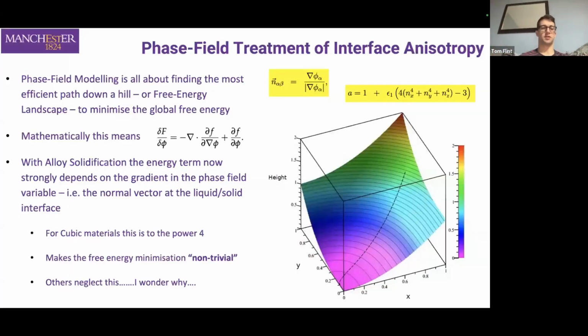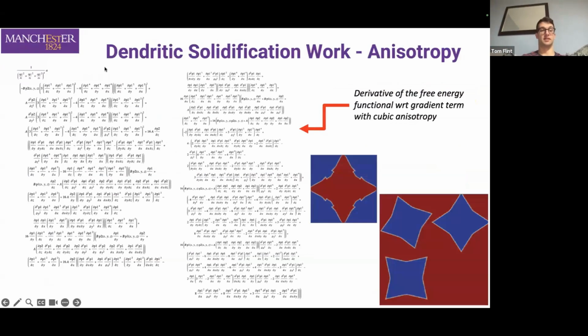Not too much on this because it's just some math, but the reason what we've done is so different is that we've actually gone to the effort of doing this. This is called the variational derivative. It tells you how you get down the free energy landscape, and this is what you're minimizing in the phase field method. This first term, the divergence of the derivative with respect to the gradient, becomes really tricky when you have gradients to the power 4. And this is the result of that. We're the first people. I went through this and did this analytically.